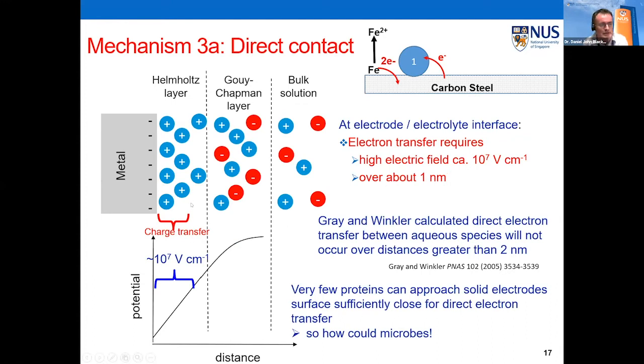We've got our Helmholtz layer and our electrons jump across there, but typically over about 1 nanometer. Really the heart of electrochemistry, as Bockris described it, is this high electric field that we have at our interface. It's 10 to the power of 7 volts per centimeter roughly. We essentially have about a volt drop across a nanometer. But biomolecules are bigger than a nanometer. You're not going to jump that far. And there's been a number of works that have shown that direct electron transfer between aqueous species won't occur over distances greater than a couple of nanometers. And there are very few proteins that can actually approach the electrode surface close enough for direct electron transfer. So it doesn't really seem viable that microbes can.